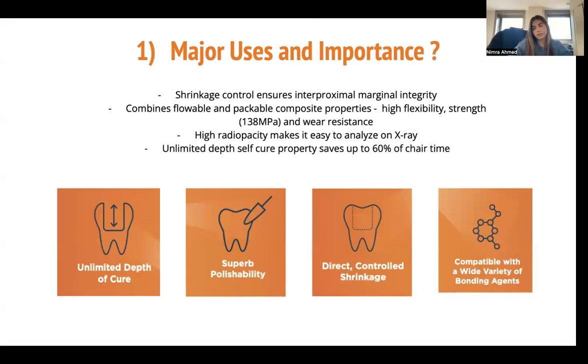So major uses and importance. Shrinkage control ensures interproximal marginal integrity. It combines flowable and packable composite properties, so we see high flexibility, high strength at 138 MPa and wear resistance. It has a high radiopacity, which makes it easy to analyze on X-ray, and the unlimited depth self-curing property saves up to 60% of chair time.